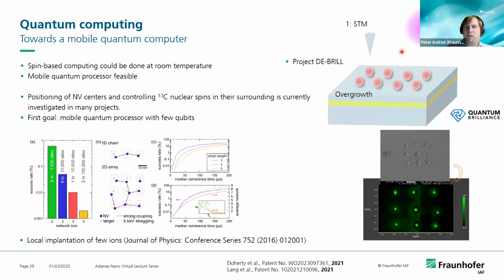So the approach is using a scanning tunneling microscope to position individual nitrogen atoms, overgrow, and by that actually getting the NV centers in very close proximity. What you see down here is actually the approach that I've shown already before. But this may in the end lead to arrays of NV centers, but this is a work in progress.